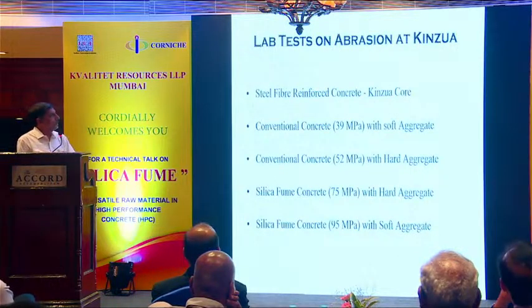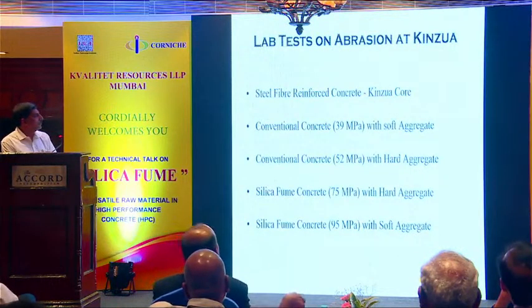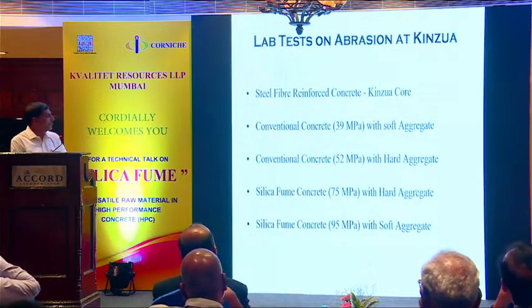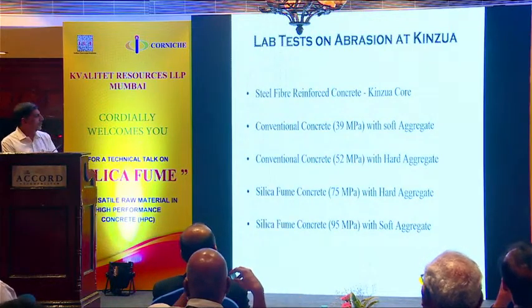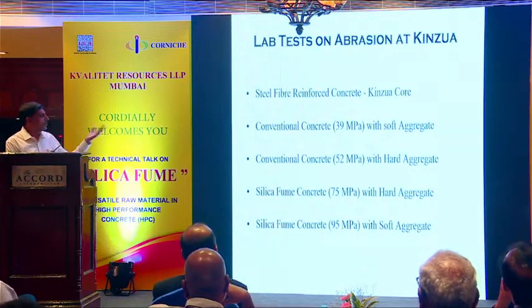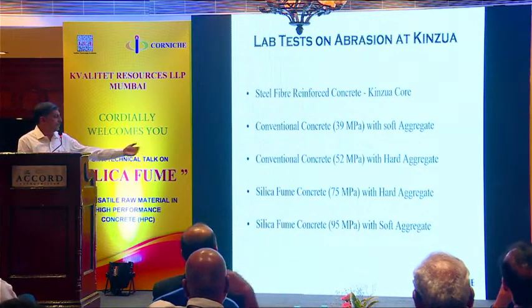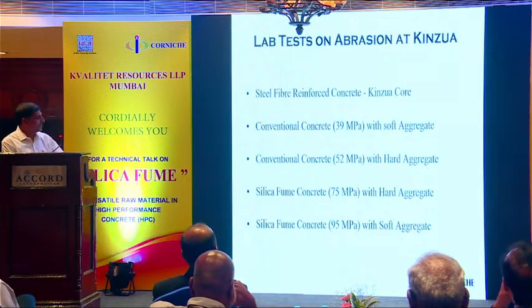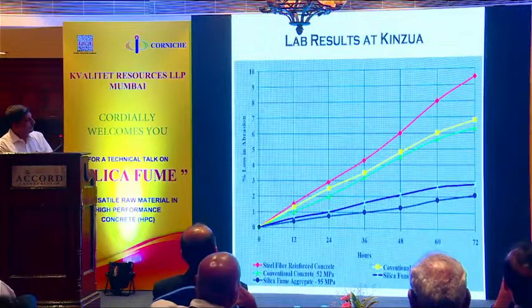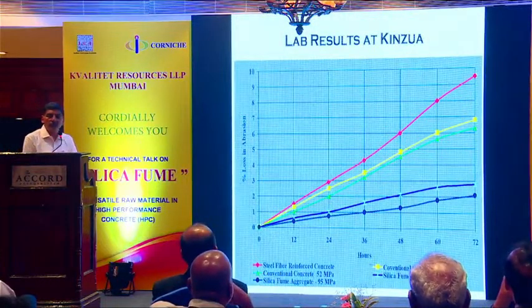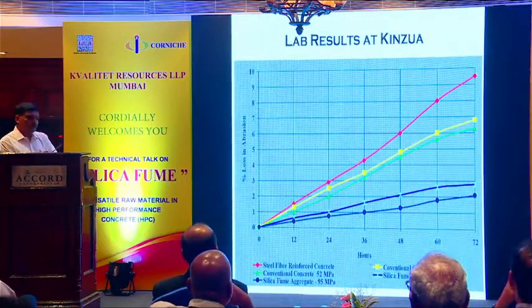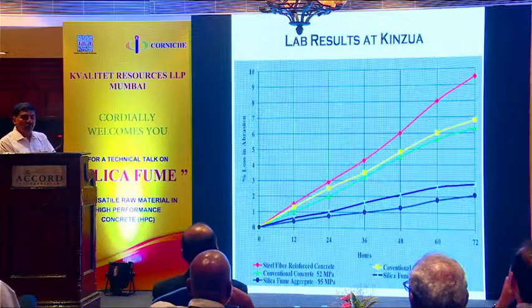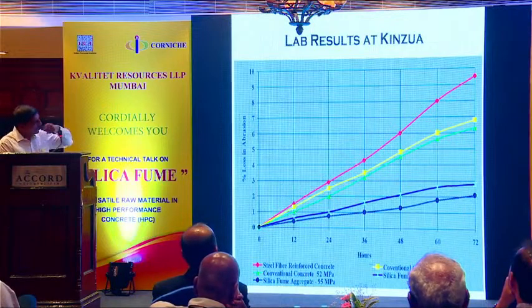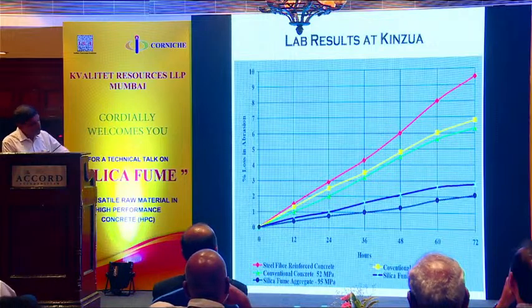So what lab tests did they do before coming to silica fume concrete? Steel fiber reinforced concrete with Kinzua, that's a local aggregate, conventional concrete with soft aggregates, conventional concrete with hard aggregates, silica fume concrete with hard aggregates, and silica fume concrete with the local aggregates. It's a 72-hour testing actually. And every 12 hours they take out the sample and see the weight loss. And the weight loss has been jotted there. See, all silica fume concrete was going flat. No abrasion and erosion there.